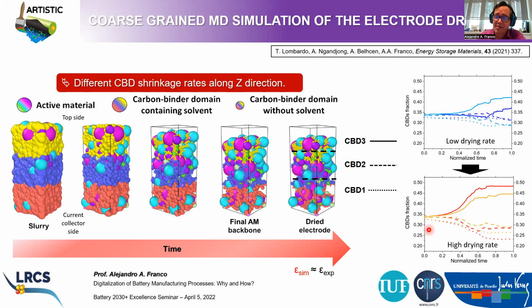And this is something that is very interesting also to capture, that the model is able to capture, is that this CBD migration phenomenon doesn't start from the very beginning. So you always have a kind of delay here, right? It starts some time after the drying process starts. And these two aspects, the CBD migration for high drying rates and the fact that this CBD migration doesn't start from the very beginning, these are two experimental facts, okay? This model is actually finding things that have already been observed at the experimental level. And this is something that we have discussed in this paper, which appeared last year in Energy Storage Materials.